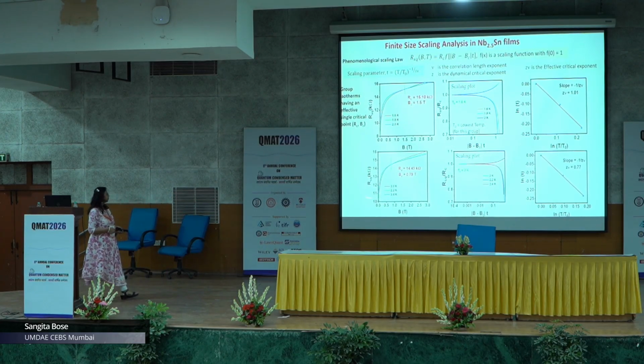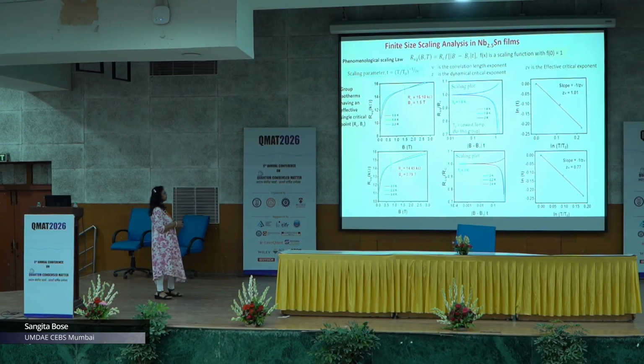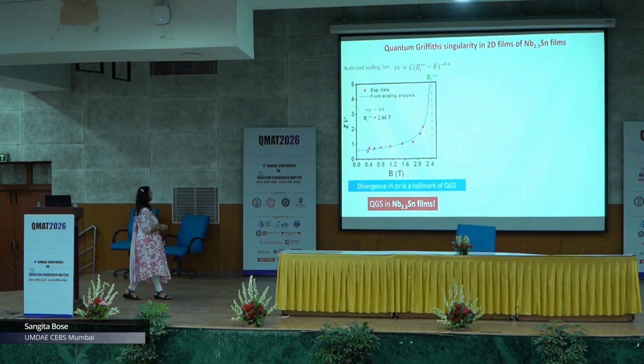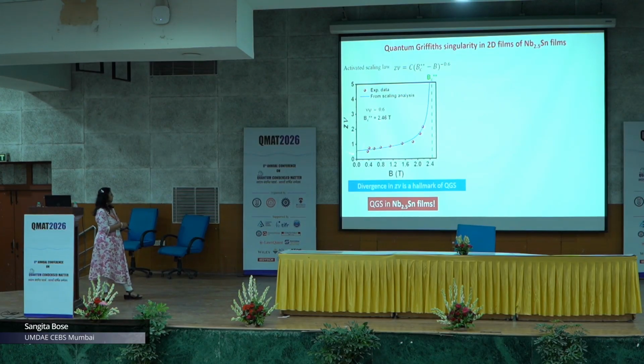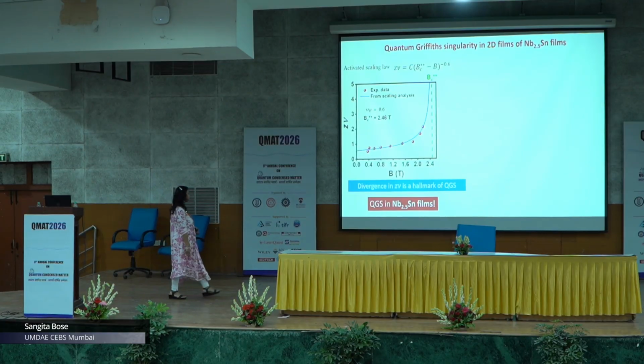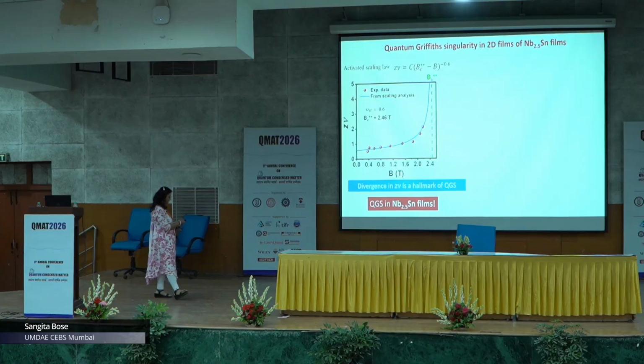So, this is another set of data for different temperature scales where you do see exactly the same thing, and you get the critical exponents for different temperatures. So, when you get these critical exponents for different temperatures, we plot this effective dynamic critical exponent zν as a function of the magnetic field, and we see this divergence, which is what we have shown you, which is the characteristic feature of the activated scaling prevalent for this quantum Griffiths phase.